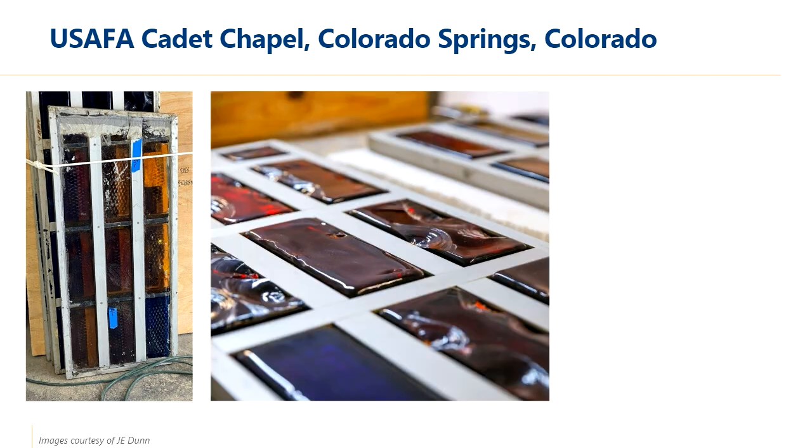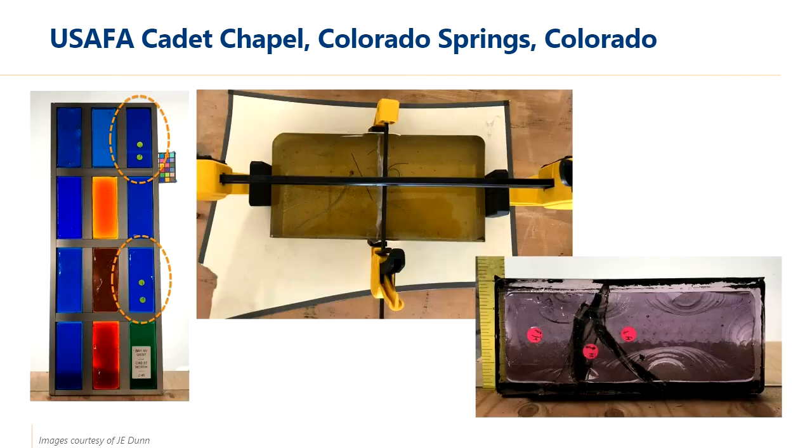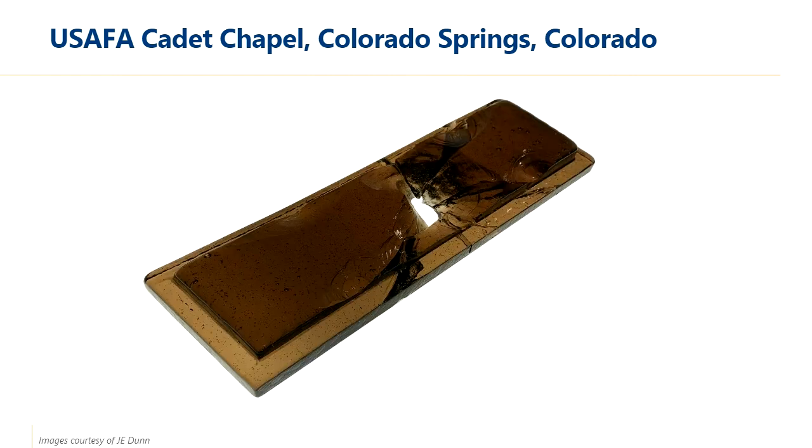So upon arrival at Judson Studios, each cassette is cleaned and each piece of dalle de verre glass is assessed for damage. To preserve the historic fabric, 300 cracked dalles were removed and epoxied back together before being reset into their original aluminum cassette. But one of the 24,384 dalle de verre glass blocks was simply too damaged to be put back together.